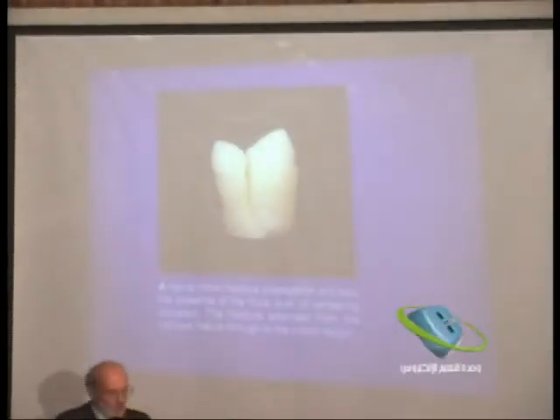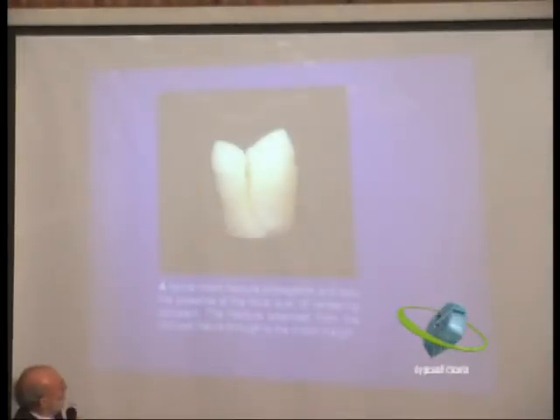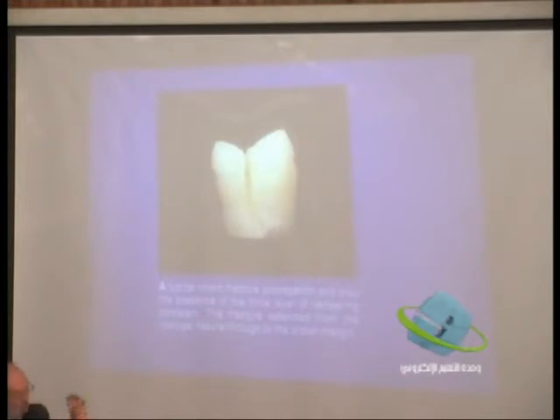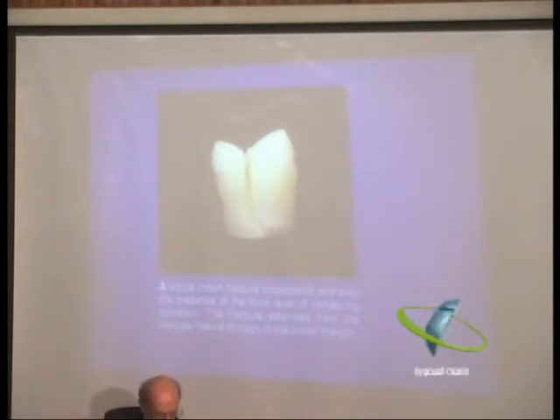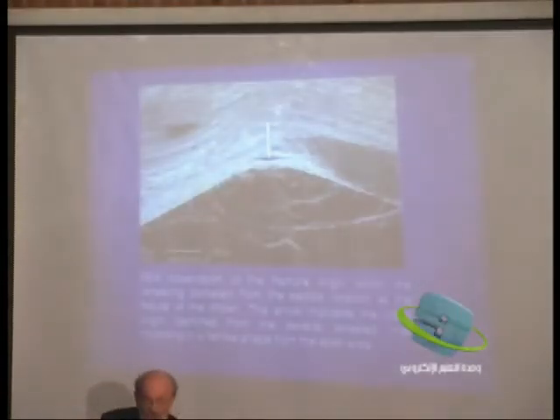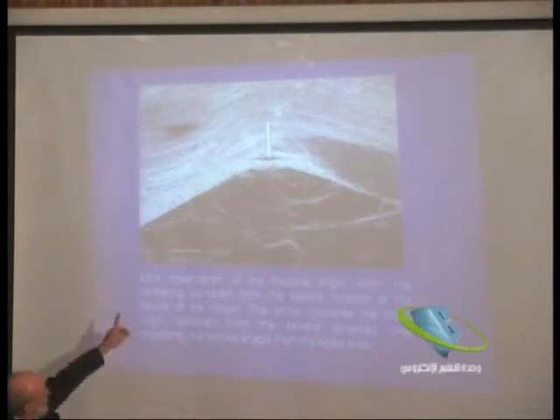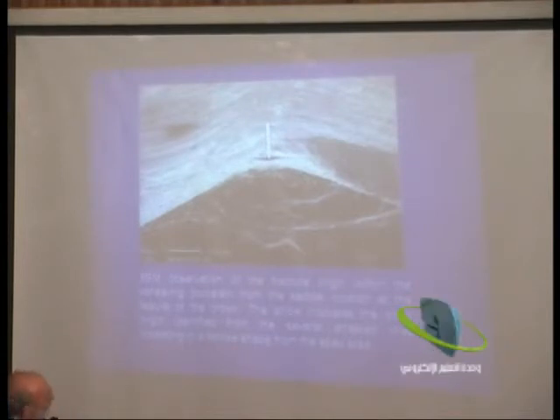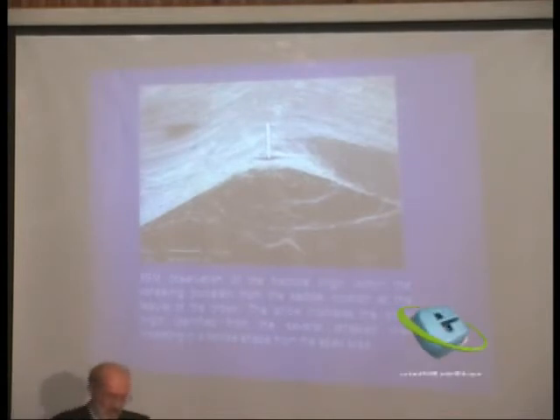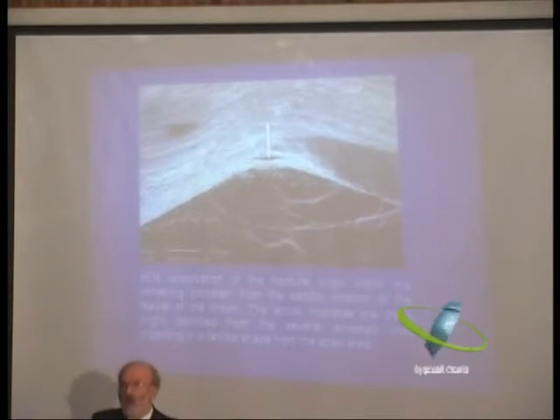And again, why was this? You can see the fracture initiated from the base of the cusp. There was a very thick layer of the porcelain material on top of that, and we were able to get quite consistent outcomes. When we looked on the SEM, we could see that the crack is initiated in this cuspal area, in the saddle point, and we could follow that crack growing down that system. So how to make progress? How do we actually interpret that?